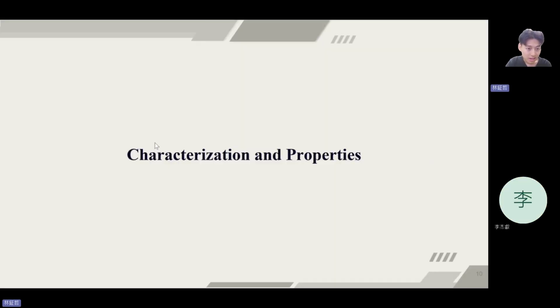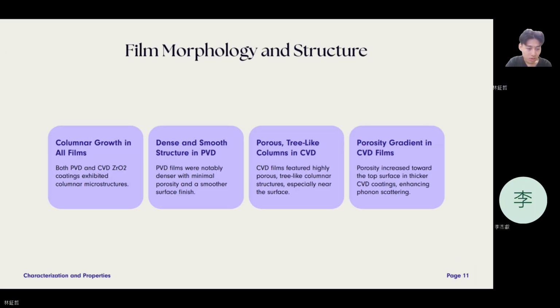Section 3. Let's look at part 3, characterization and properties. Morphology. First, we look at the film morphology and structure using a microscope. We found that both PVD and CVD films grow in columnar shapes. However, they look very different. The PVD films have a very dense and smooth structure. They have almost no holes.